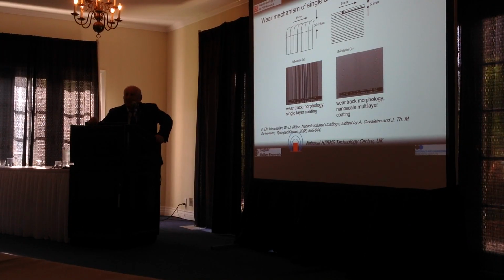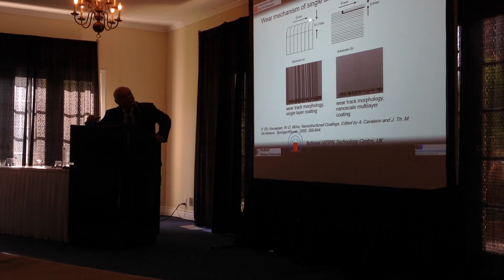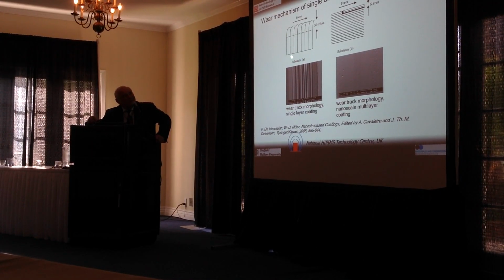What we also liked was the behavior of these layered materials in tribological applications. So this is the friction force in monolithic materials, in monolithically grown materials. You can easily open tensile cracks at the column boundaries. You can release huge particles which act as third body in the sliding contact and produce these very grooved wear tracks. Whereas nanoscale multilayers tend to deflect cracks, they produce very fine wear debris, and therefore you end up with very fine surfaces.